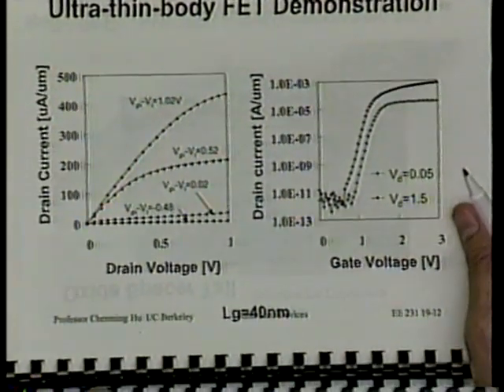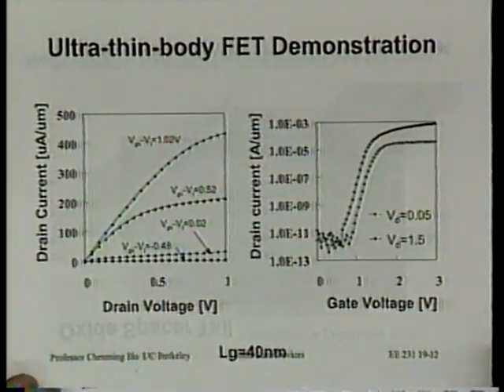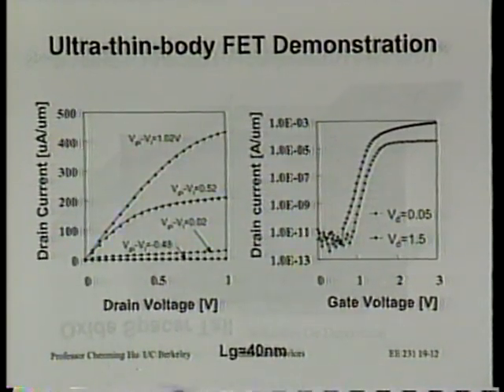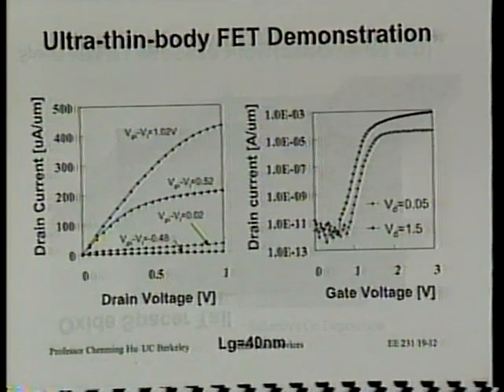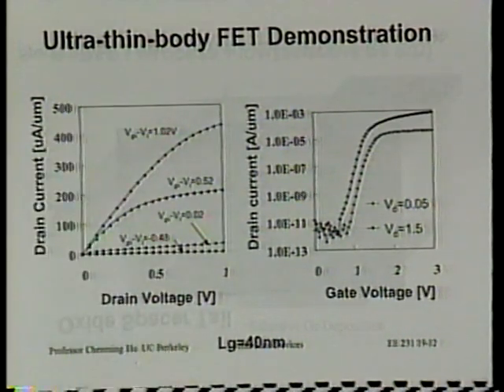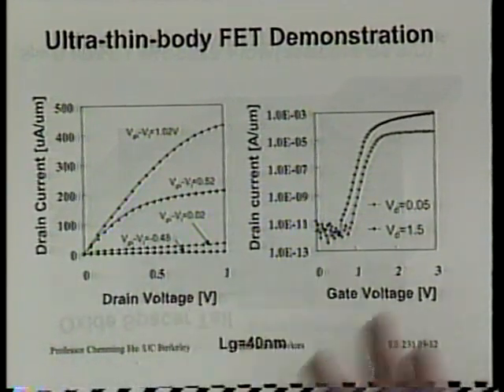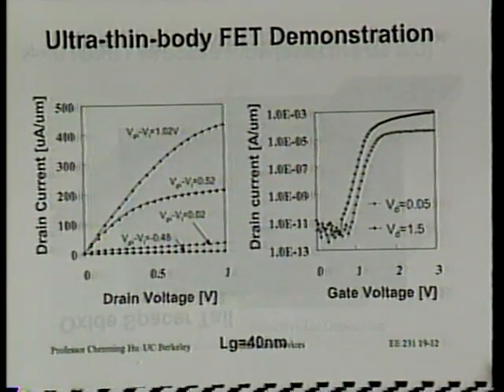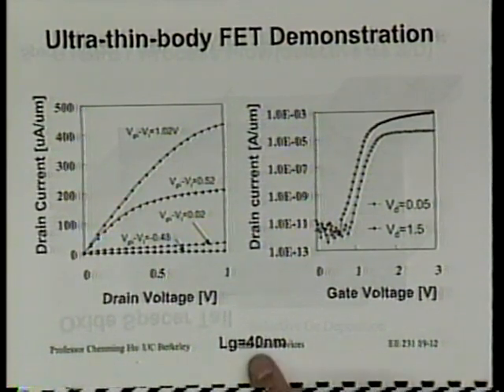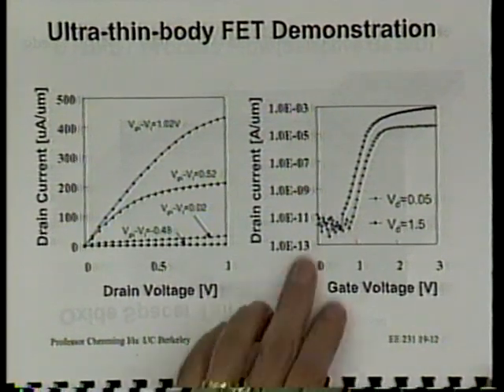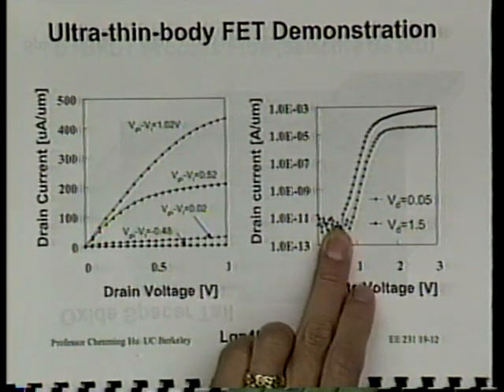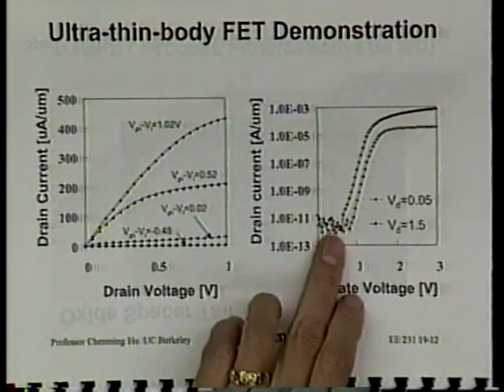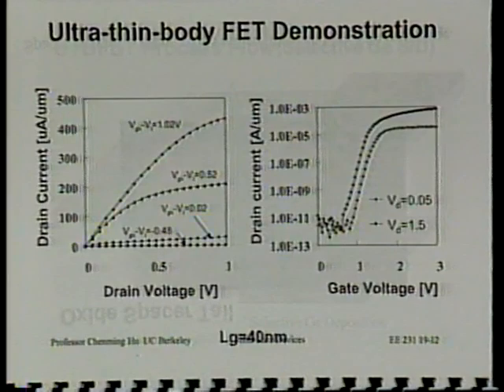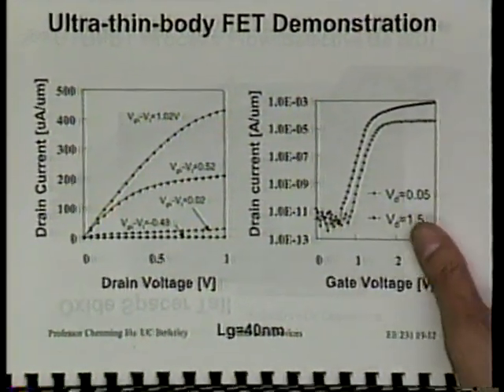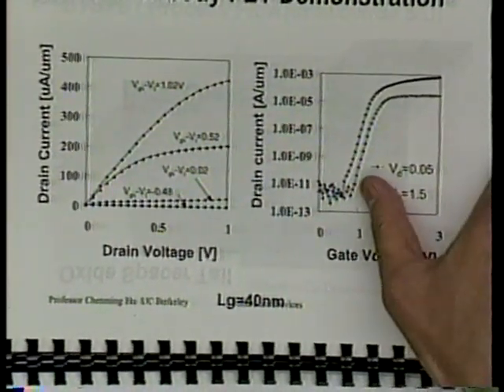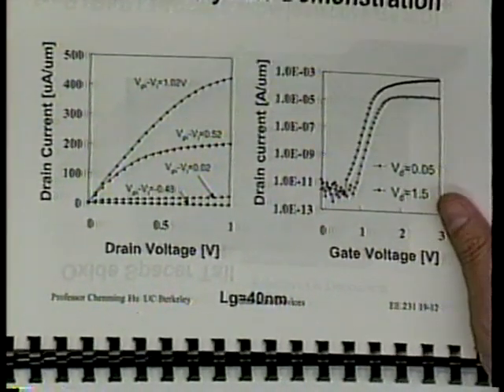And so here's some performance that he was able to get. This is not the best data, by the way. Every 2 months, he and Day One, working with Yang-Kyu, have some better data. So this current keeps increasing. But this is from last year. For a gate length of 40 nanometer, and we're convinced, with such good low leakage current at 40 nanometer, if we can make them at 20 nanometer gate lengths, I think it can scale to that. You can see that, right? There's no evidence of drain-induced barrier lowering or any other leakage.